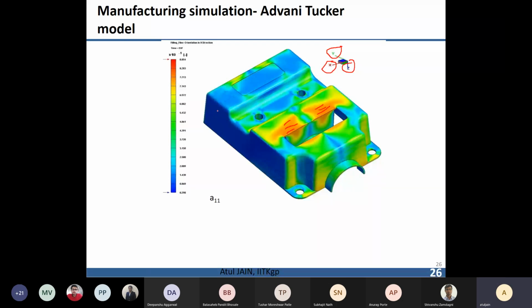And in some direction, the fibers are highly aligned in this direction. And there are lots of regions in between. Highest A11 is 0.88, almost fully aligned. If this was 1, all the fibers would be fully aligned, and lowest is 0.298. In the other two directions, maybe the orientation. But by looking at this image, you can see point by point, the orientation is varying. Okay.